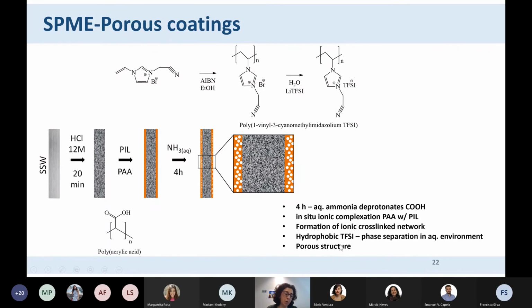The porous coatings was again a cooperation with a university in Sweden, with Professor Yanyan Wang. And here what we did is we used a polymeric ionic liquid and a polyelectrolyte, and we activated the polyelectrolyte by a pH change. So we have here our polymer and our polyacrylic acid, and we prepare them. So we have a stainless steel wire. We etched it with HCl solution. We coated it with this solution, with the polymeric ionic liquid and the polyacrylic acid. We put it in an ammonia solution for 4 hours.